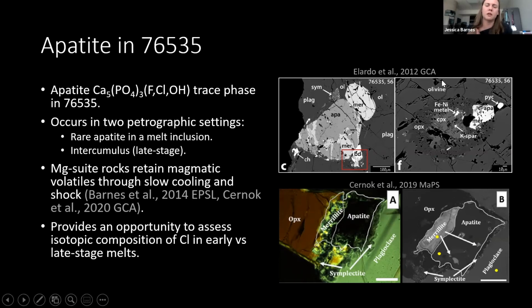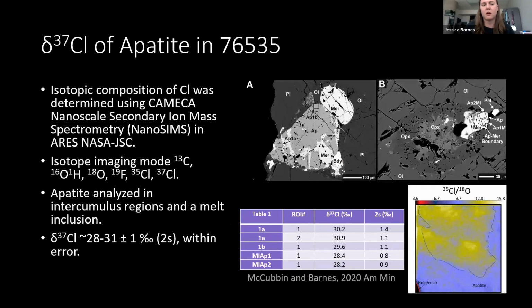And so what we wanted to do in this study was compare the chlorine isotope compositions of the intercumulus grains and the melt inclusion to see if we could identify any magmatic or crustal processes happening that could be fractionating the chlorine isotopes. And so by looking at the melt inclusion, we were hoping we were going to see a magmatic signature, or an initial or original signature for that melt. And so we used the NanoSIMS at NASA's Johnson Space Center to do this work, and it was published last year in American Mineralogist.